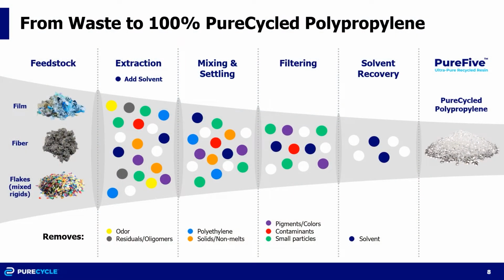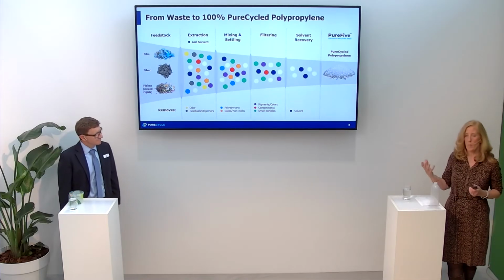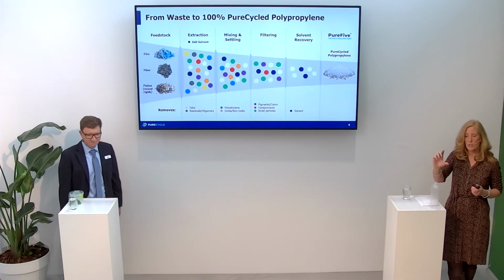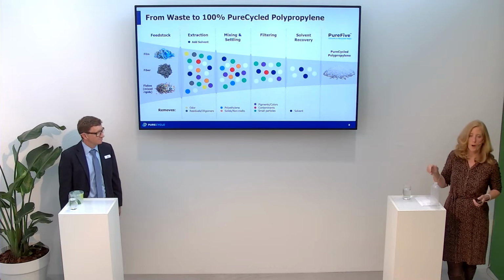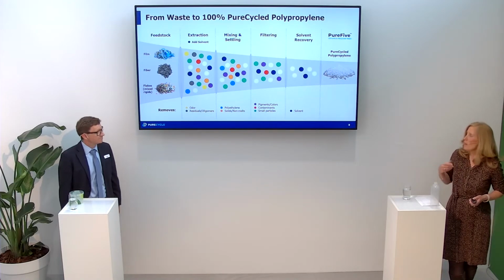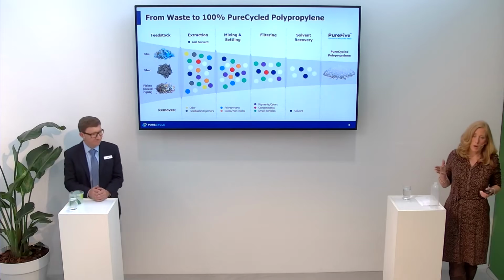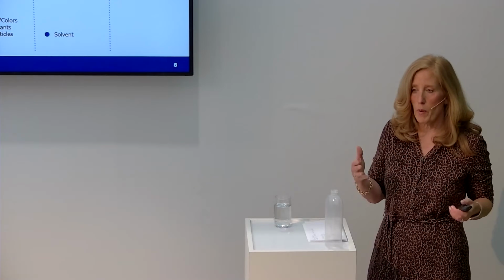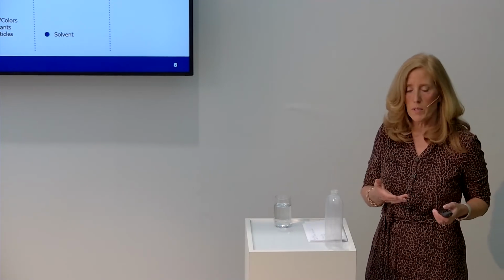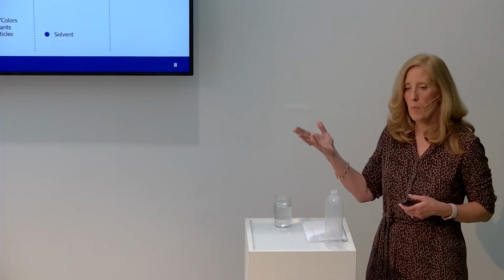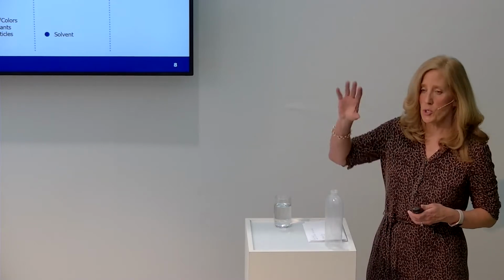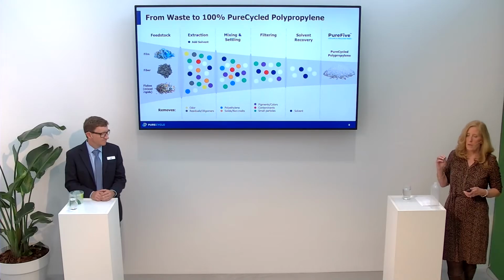So you can see we have different formats that can enter in polypropylene. There's woven and non-woven polypropylene. There's rigid containers. And there's fibers like carpet and things like that. You can see in our kit, the very first sample is black showroom carpet from a conference that we recycled. All those inputs go through what we call a pre-processing system, whether we shred and separate the different polymers in mixed rigids that we see, or we take in a shred and agglomerate fiber or film. We put that into our system, and then we extract the oligomers and the organics and the odors and the dyes in our first step.